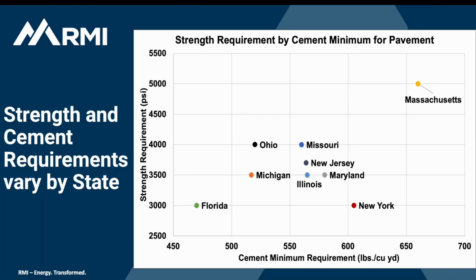Further to this, we found that different states are achieving similar strength requirements with varying minimum cement requirements. This graph shows a comparison of the strength requirements on the y-axis versus the minimum cement requirements on the x-axis. For example, Florida and New York have the same minimum strength requirement of 3,000 psi. However, Florida has a minimum cement requirement of 470 pounds per cubic yard, while New York has a minimum of 605 pounds per cubic yard. What does this mean for the potential emissions of these states? That's what we at RMI are trying to find out.